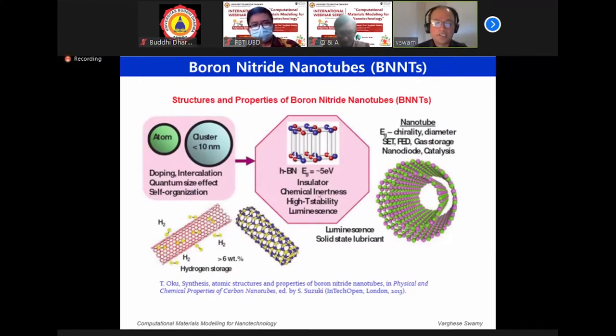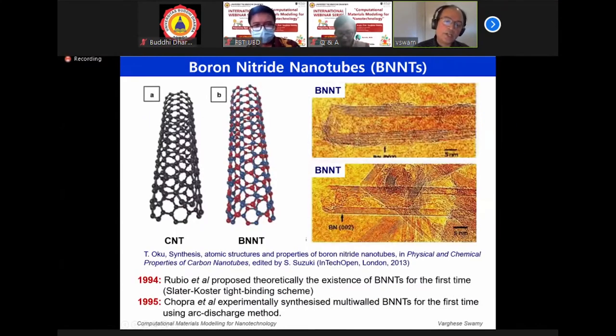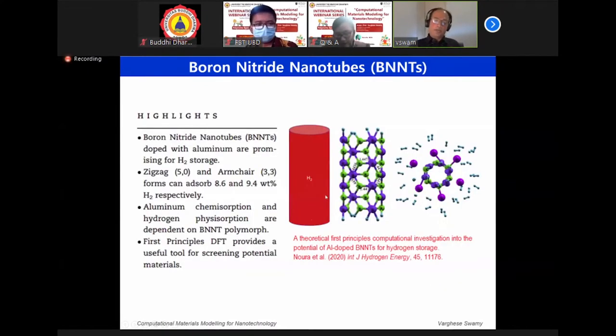I'll probably quickly just show one or two slides on BNNT, which is boron nitride nanotubes, which are important for many applications, including hydrogen storage and drug delivery. And BNNT was initially predicted based on carbon nanotube structure in 1994 using theoretical calculations and later experimentally synthesized. And that's the case with some of the materials which I was talking about earlier. Here you can see a high resolution electron micrograph showing the BNNT structure. If you dope the BNNT with aluminum, you are able to store a significant amount of hydrogen.